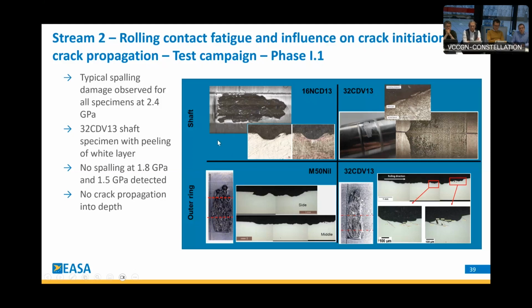You see it here, we made pictures from the spalling damage. You see also the scratch here. The mouse is a little bit slow, so I try to go over it. And then we always evaluated these damages by metallographic cuttings, also to look whether we see some subsurface cracking, and you see it here. The cracks are resting always at the same final depth here at the end. But at the end, it was always spalling.